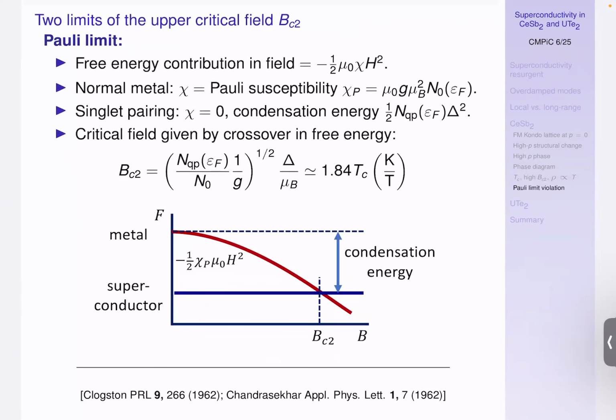The important thing with Pauli limiting is that if you have a singlet superconductor, there's a limit to the field at which it can sustain the singlet state, because it's advantageous for the singlet to break up so that you can exploit the full Pauli susceptibility of the material. The free energy contribution in field in the normal metal would involve the Pauli susceptibility. But if the susceptibility is basically zero because the spins are bound into pairs of singlets, then you lose that, but you gain the condensation energy from being superconducting. So there's a crossover between the two curves: either the superconductor, with no field dependence but starting out at a lower energy, or the metal, where you gain by letting the spins flip. That crossover is the Pauli limit field, and it's usually basically proportional to Tc.